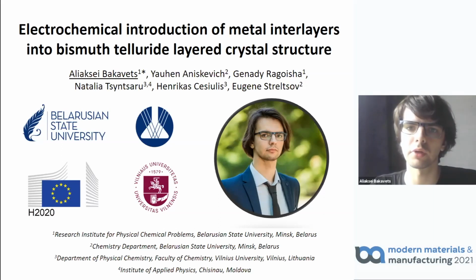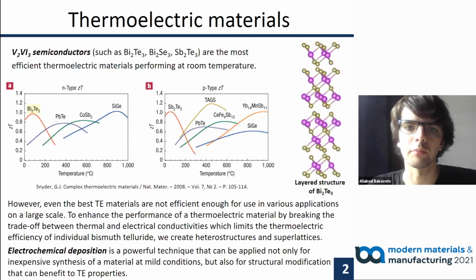Let me introduce you to my research related to electrochemical fabrication of bismuth telluride-bismuth superlattices for thermoelectric applications. Bismuth telluride is one of the best thermoelectric materials at room temperature, but the thermoelectric figure of merit, even of bismuth telluride, is insufficiently high for most thermoelectric applications on a large scale.